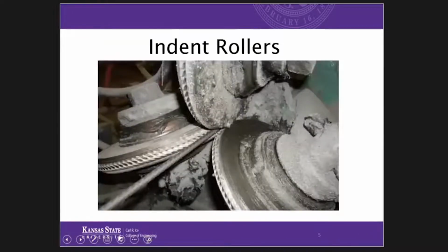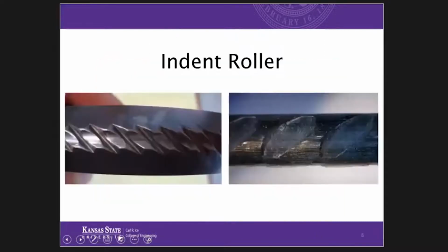So when a pre-stressing wire is manufactured, it starts out as a rod and goes through a series of dies. We get the work hardening that gives us the high tensile strength. And then at the end of that process, it goes through 3 indent rollers that create the actual indent profile within it. This slide shows the indent roller on the left that pushes into the wire, which leaves the indentations shown on the right.